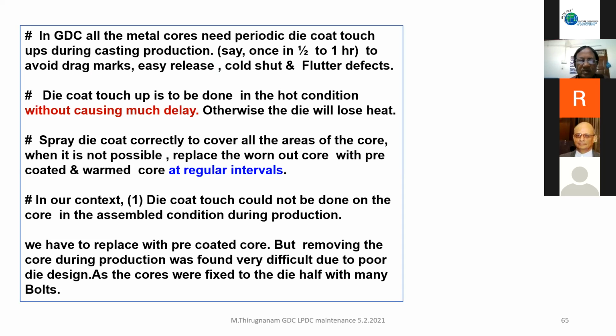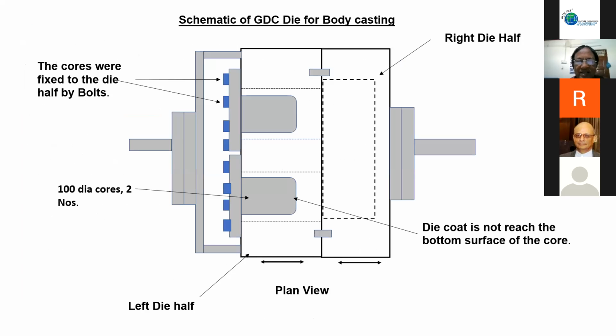And then I told them, let us go and see what the problem is. The operators were seriously running the die for hours together and producing castings, and we found in the bore a lot of score marks. Then we suspected there was something wrong in the core. Dismantle the core assembly. To my observation, they took about 45 minutes after dismantling about 16 bolts.